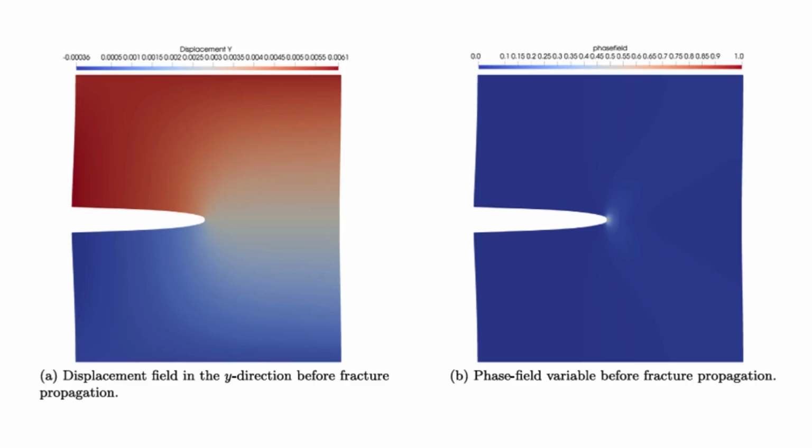That's where the phase field method, PFM, comes in. It sidesteps that whole issue. What's the trick? It introduces a new variable, usually called phi. Think of it as a damage indicator. But instead of being sharp, it's smooth. So not a clean cut, but more like a gradient, a fuzzy zone. Exactly like that. Phi goes smoothly from 0, that's perfectly healthy material, all the way to 1, which means fully cracked, completely broken. And because it's smooth, this damage field can spread, it can branch, cracks can merge, all without ever needing to rebuild that underlying mesh. The grid stays fixed. That is clever. Smooths out the problem, literally.